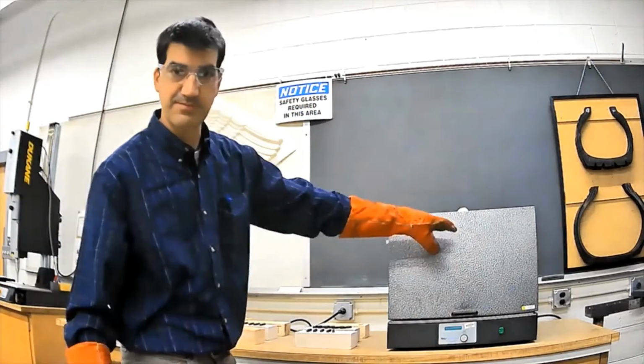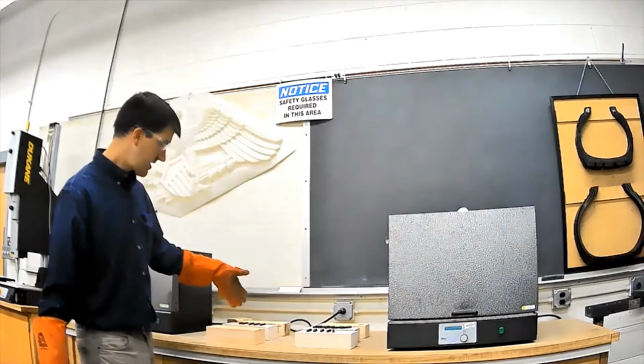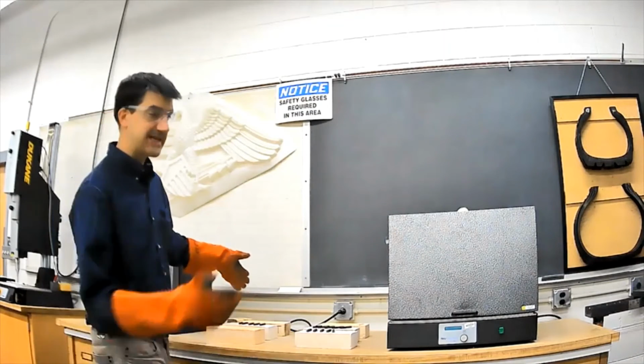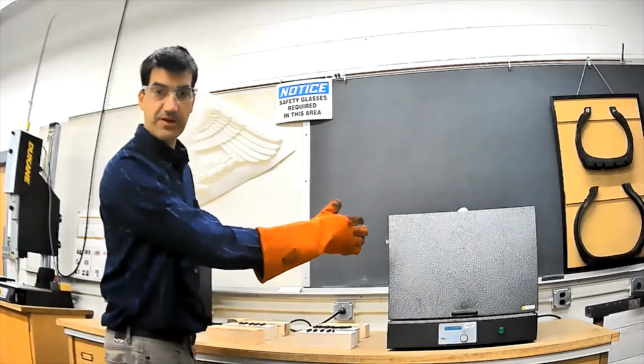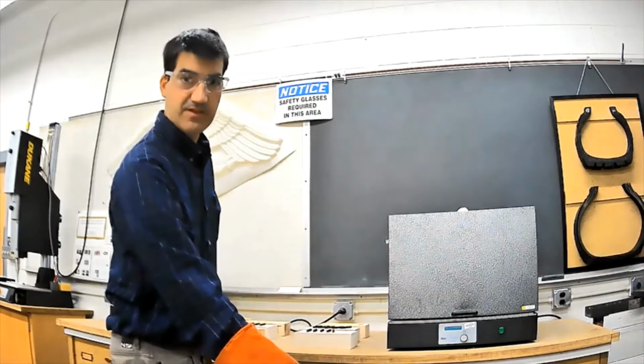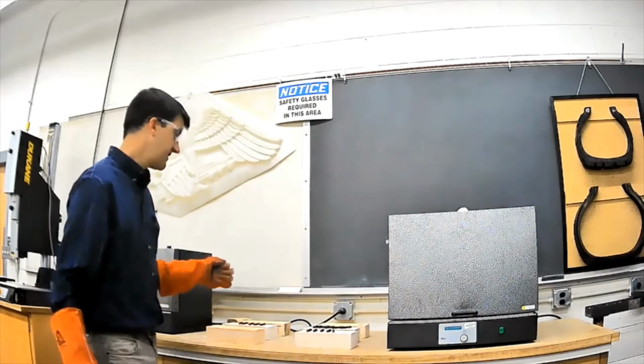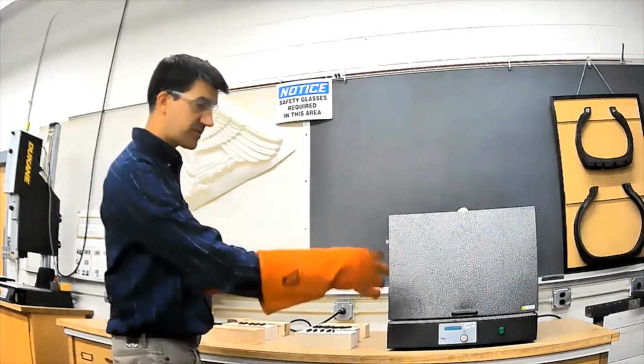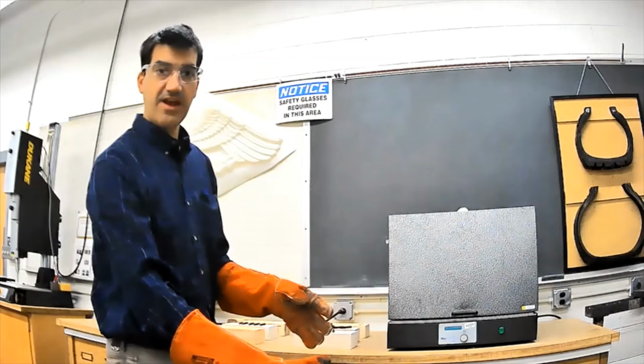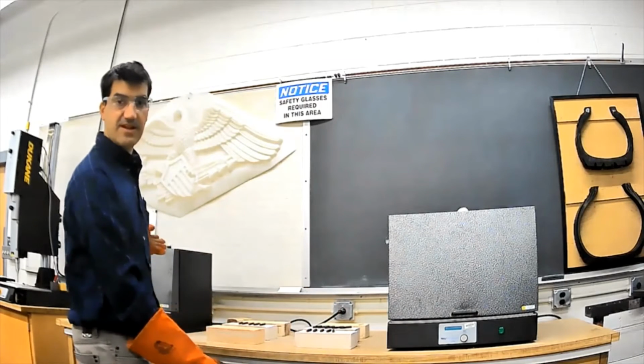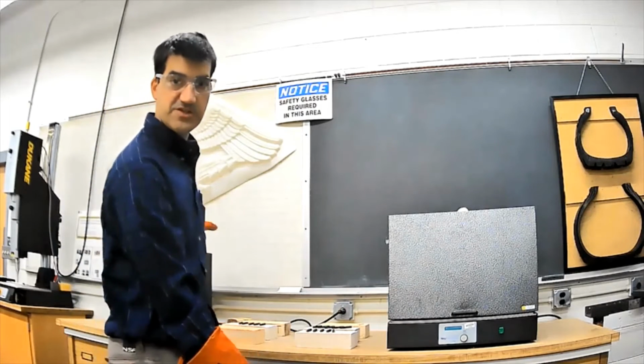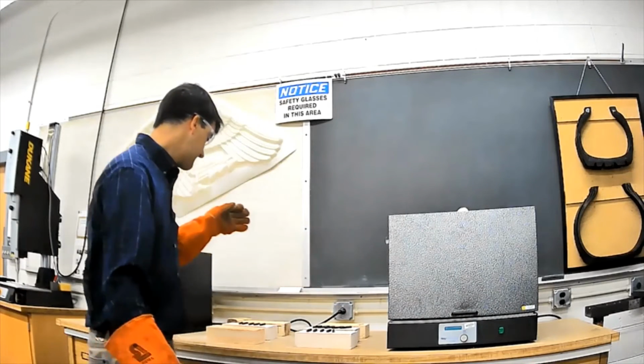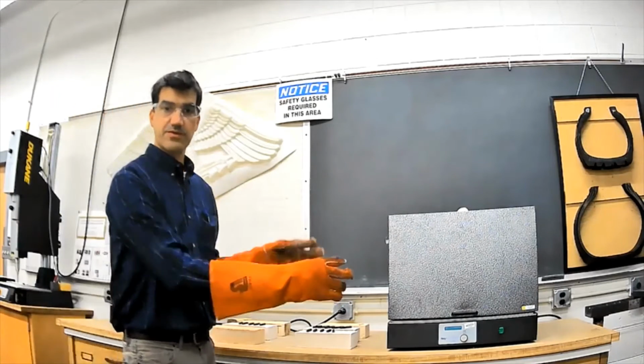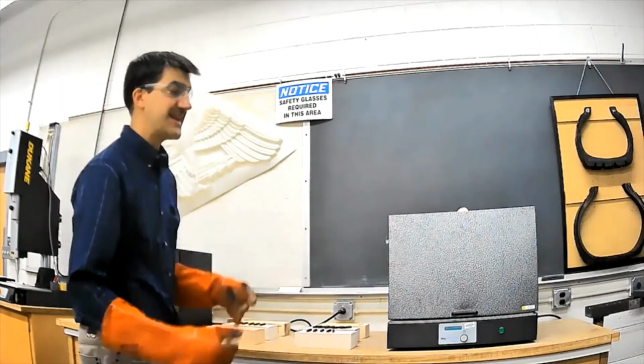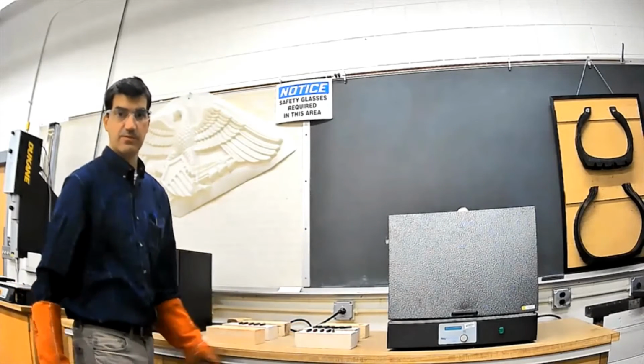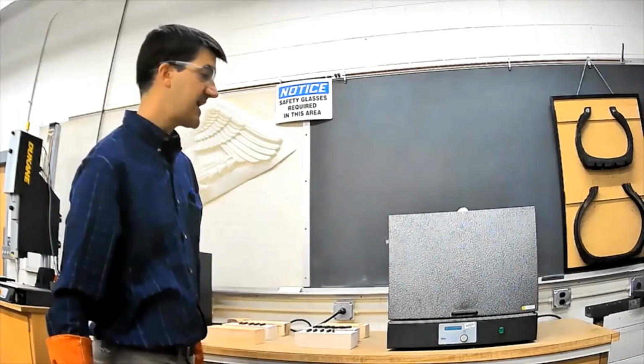All right, so to review, we got these 3 specimens here and 1 set of specimens here. We got specimen 1 up here. This was the one where we heated it up to a really high temperature above the upper critical temperature and then water quenched it. So we hardened it and water quenched it. Specimen 2 is the one that we hardened with a water quench. And then after that, we tempered it in the low temperature furnace. That's the one we just got finished doing. So that's specimen 2. Specimen 3, we hardened with a water quench as well. But now we are annealing it. So that's what we're doing in the high temperature furnace right now.